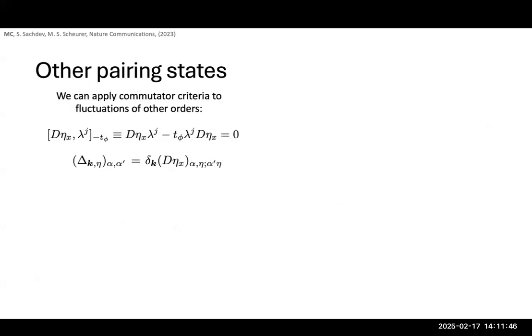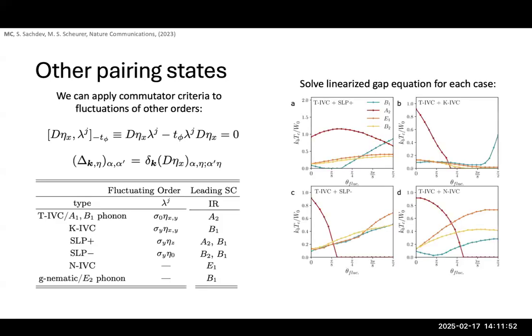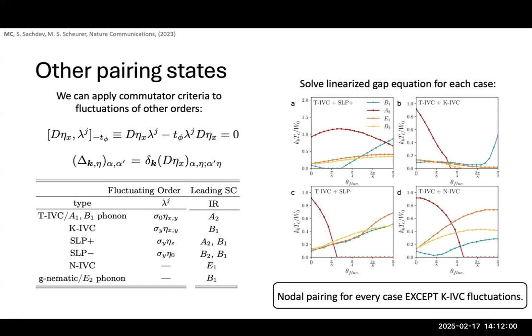And so we also did this for the other types of fluctuations we can consider. We apply our same commutator criteria, and we compare this to what we see from solving the linearized gap equation. And effectively what we find is that all of these types of fluctuations besides the K-IVC and nematic, and phonon, give you some state which has a nodal regime. So basically in terms of ruling things out at a mean field level, we can really say this and this are not so compatible with experiments.